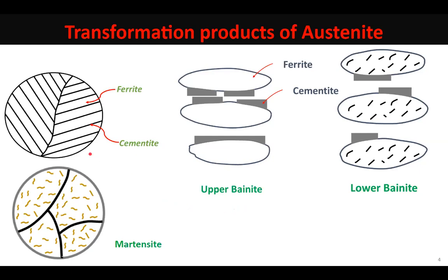So this is the pearlite structure, always a lamellar structure unless you do something special with it. We have a lamella of ferrite, an alternate lamella of cementite, then ferrite, then alternate lamella of cementite. When does it happen? At high transformation temperatures, when austenite transforms due to diffusion, and carbon and iron atoms of austenite both take part in the diffusion, then austenite transforms to what is called pearlite.